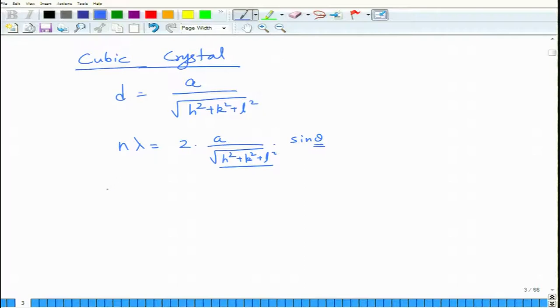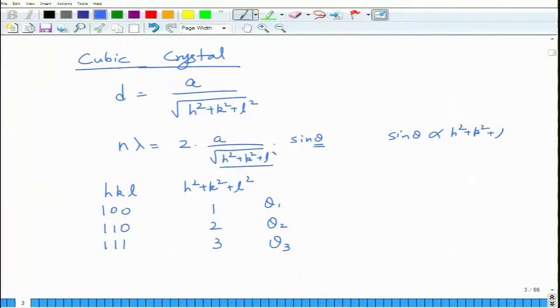So when you go through various hkl values, you start from 100, your h square plus k square plus l square will be equal to 1. What is the next value for h square plus k square plus l square? That is 2. So this will be theta 1, this will be theta 2, and as you go to, what is the next one? 111, this will give you a value of 3. So for this, h square plus k square plus l square is the smallest, theta 1 will be the smallest. So basically you can see that sin theta is proportional to the square root of h square plus k square plus l square, right.